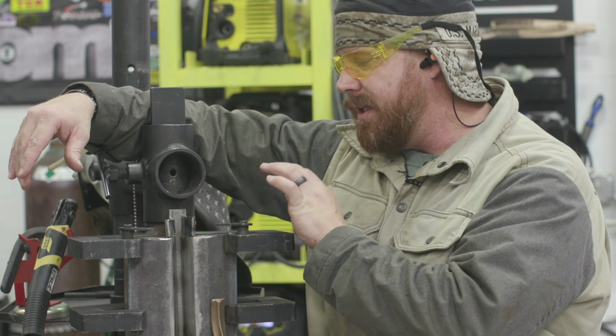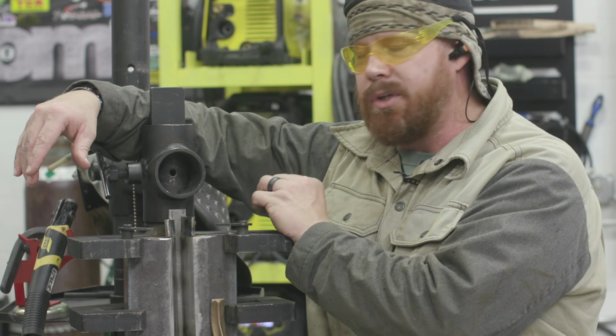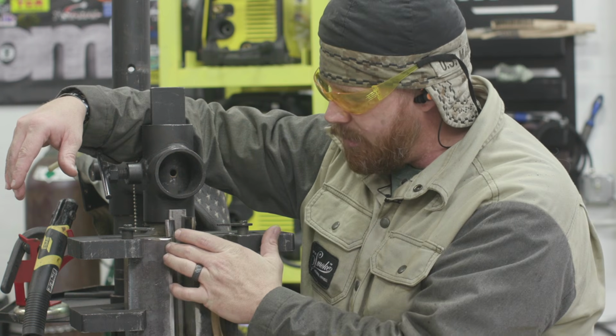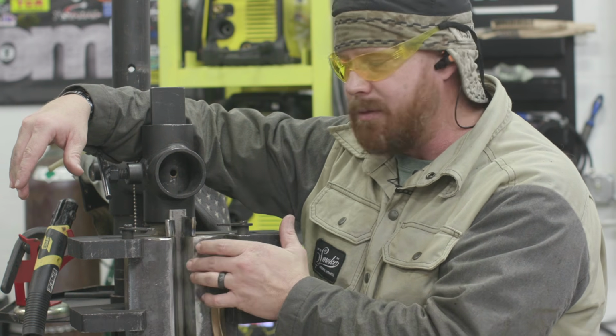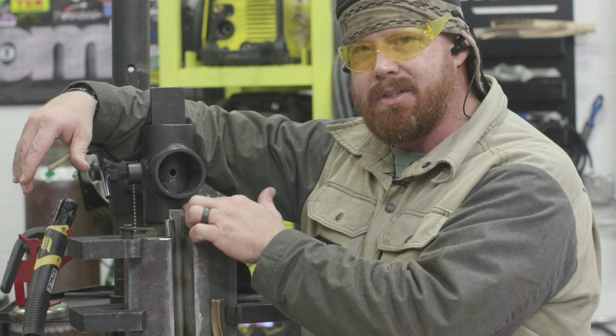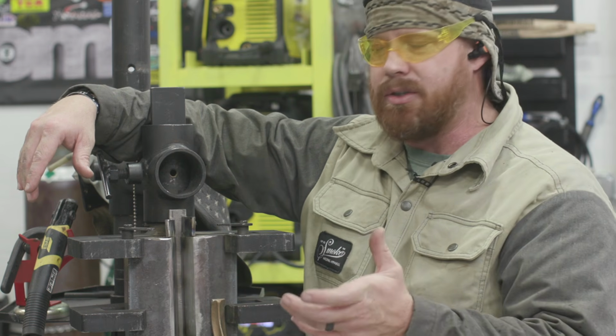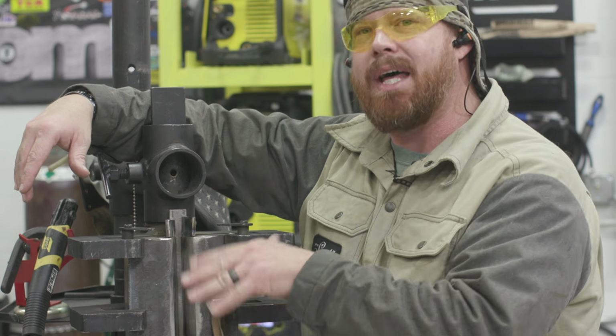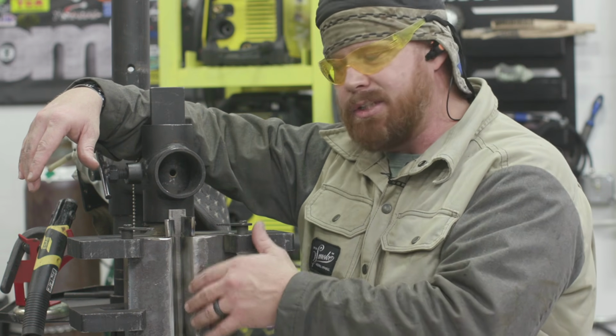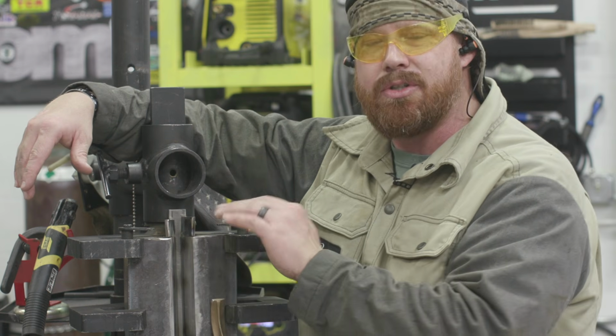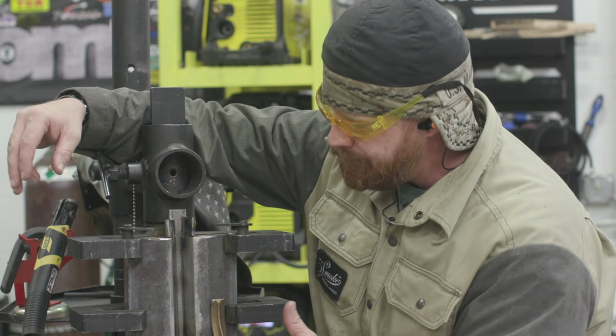One thing I do want to note is take careful consideration when you're doing all your prep work. I've already removed all the mill scale from the areas where I'm going to be welding, front and back, as well as the backing strip. Then I went ahead and took a flapper wheel and polished that up just a little bit more, which makes it a little bit smoother. I have a knife edge in here, so there's no land whatsoever on the bevel.